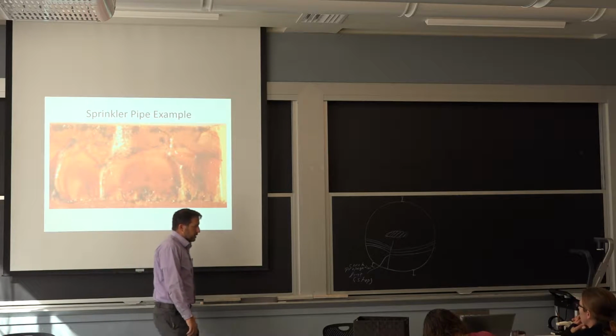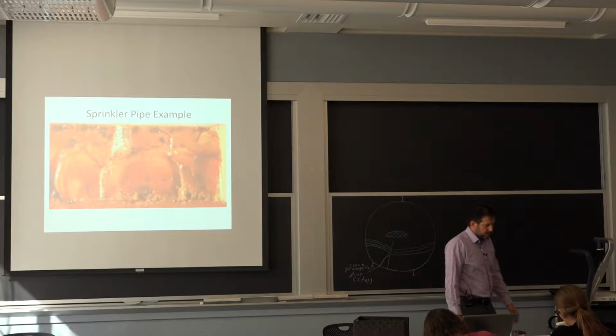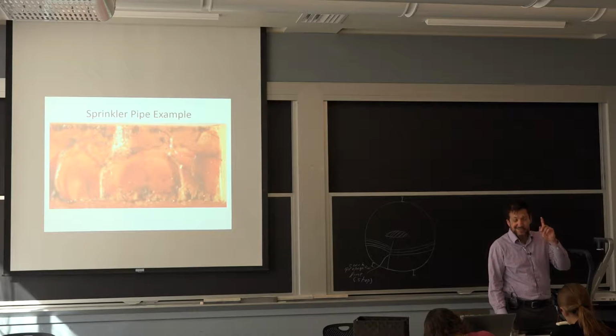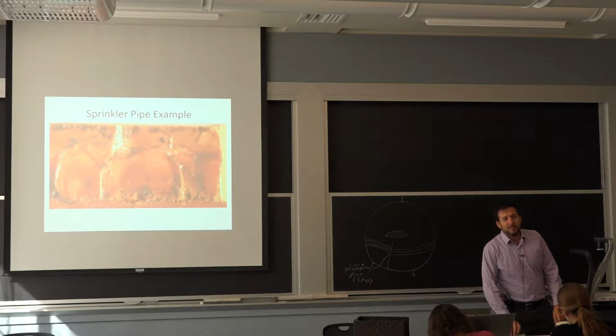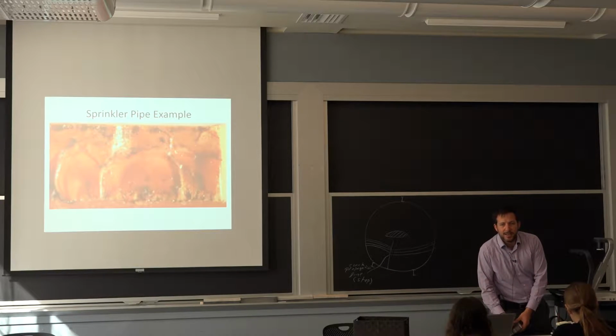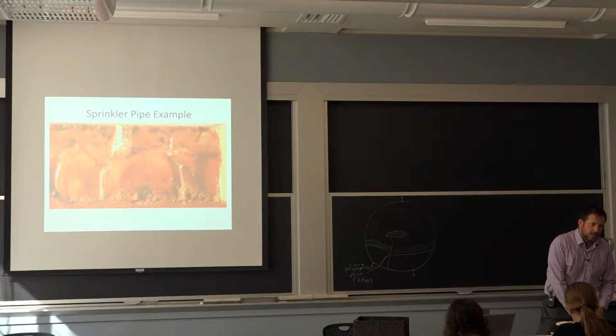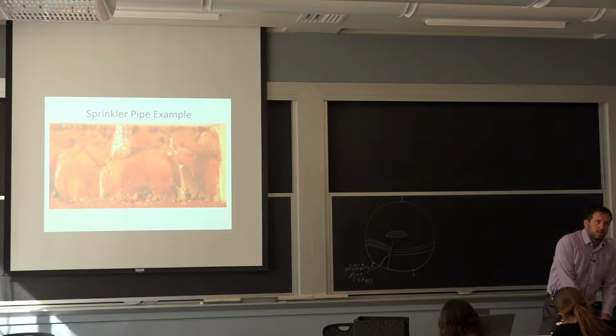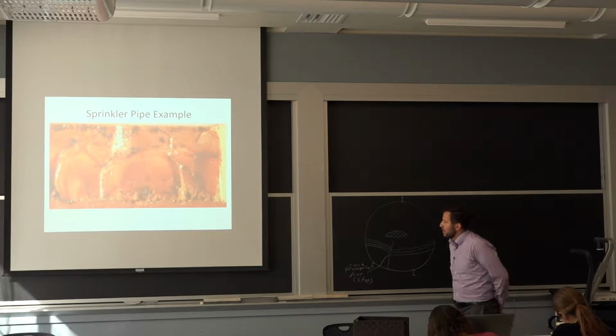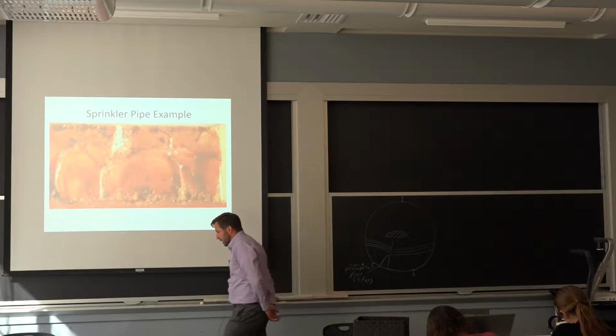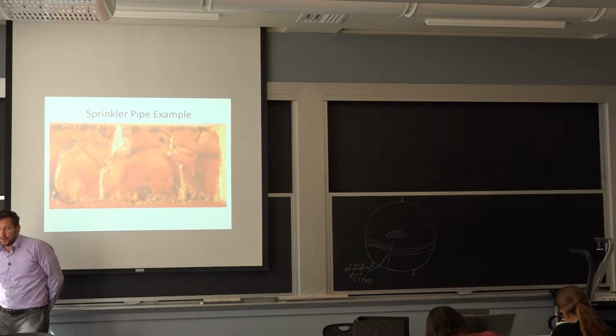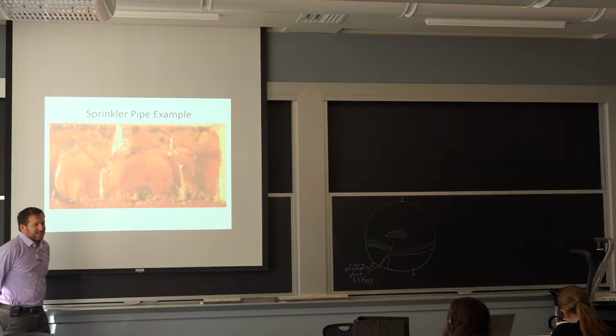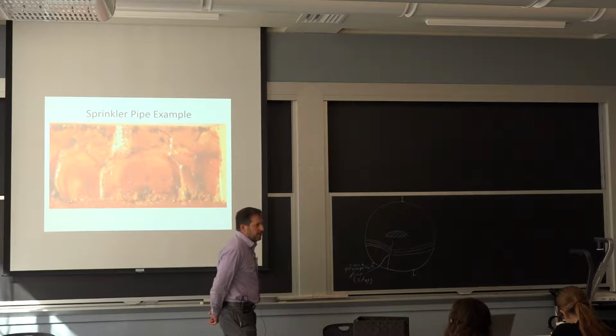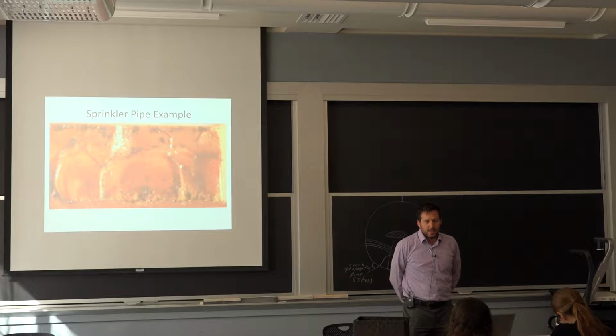It's something that comes up over and over again in failure analysis. When I have one initiation site, yeah, there's probably something very special there. But when cracks are initiating everywhere, it's either there's too much stress, or in this case, that the environment is contributing to the initiation of the failure. So what do we do about it? Again, you can ask the plumber not to use any lubricant. There's nothing wrong with asking, or at the very least, make your material as resistant as you can to contaminants that you can anticipate in plumbing.